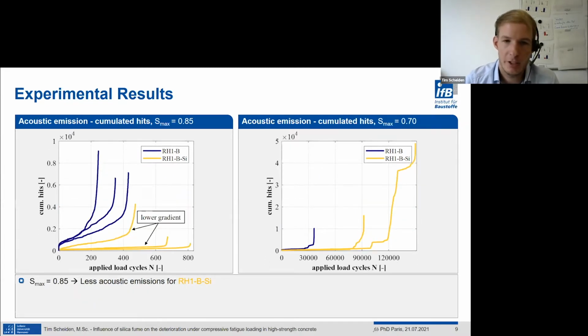The last selected damage indicator I want to present is the acoustic emission, respectively the cumulated number of hits. One hit is defined as a single transient signal recorded from one sensor. At the higher stress level on the left side, both concretes show a typical S-shaped curve similar to the strain development. But due to the addition of silica fume, absolutely fewer hits over the fatigue process and fewer hits per cycle in phase 2, meaning a lower gradient, are detectable. Also, the transitions from phase 2 to phase 3, meaning these transitions here and here,